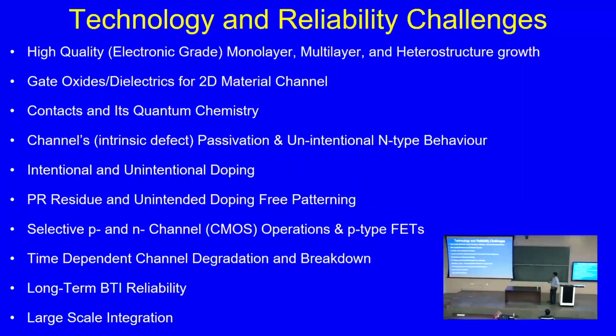Contact is a very fundamental challenge which a lot of people have worked on. Now channels, so making the channel intrinsic is also a challenge. For example, in the experimental world, you would see papers saying that 2D materials are intrinsically n-type. Now they're not intrinsically n-type, intrinsically they are intrinsic, but they behave n-type because of sulfur defects, and these sulfur defects create donor states in the presence of oxygen and moisture. This is something which we found.